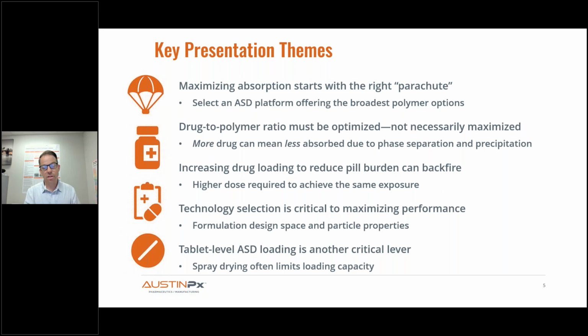Further, increasing the drug load to try to reduce pill burden can backfire, as we saw in that first example. They increased the drug loading from 15% to 50%, and required a much higher dose than if they were to decrease the drug load down to 15% in the correct polymer. Finally, technology selection, as I will cover in depth towards the end of the presentation, is really critical to maximizing